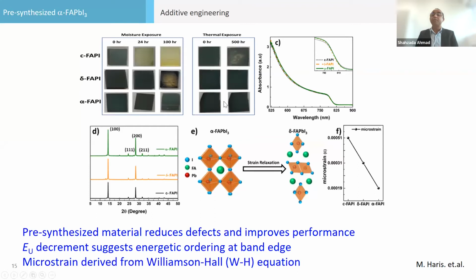Similarly, with thermal exposure, it stays black. There is no change in the absorption, but it is more stable. Then we calculated the microstrain, and this microstrain is less. The crystals are more robust. They are like shock absorbers; they can absorb more shock. And then we saw that the Urbach energy is also following a similar trend.